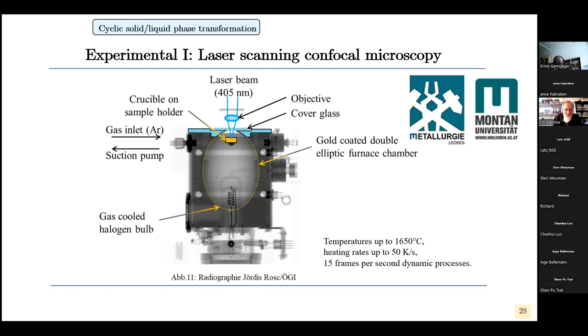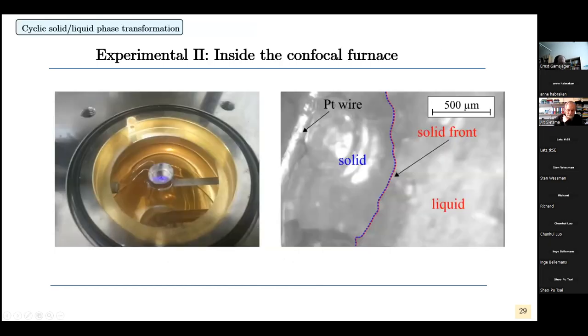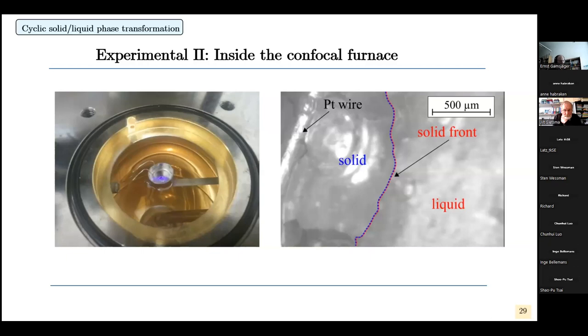We look inside the oven. This is the platinum crucible with the thermocouple. Before the experiment starts, the powder comes in and will be melted at the high temperatures. Here is a platinum wire where the solid phase can nucleate, and then we have the solid-liquid front which grows or shrinks.